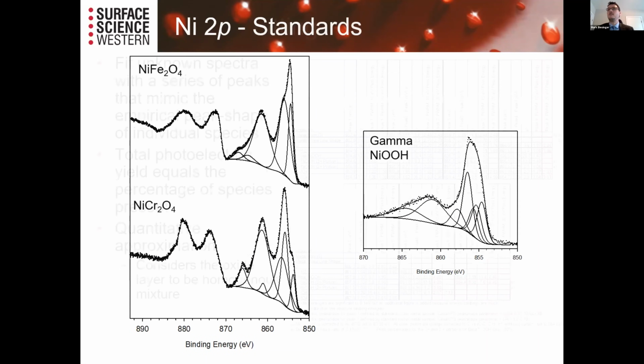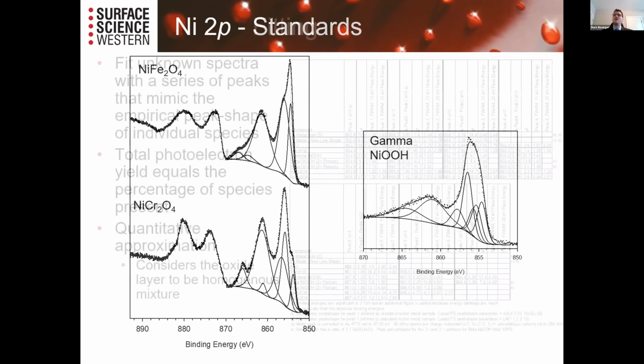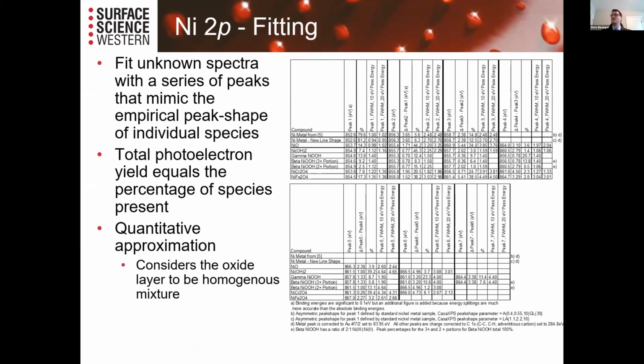So what you end up getting is these large tables that define these peak fitting parameters. The reason why we do it this way is so that we can take these fitting parameters and apply them to a whole bunch of different software packages that are used by different XPS practitioners. If we were to just use overall peak envelopes, it wouldn't work, because different instruments have different resolutions. It doesn't allow you to slightly shift the spectra around if you have some changes in calibration or changes in what you use as your binding energy calibration. And so doing it this way allows use by everyone.